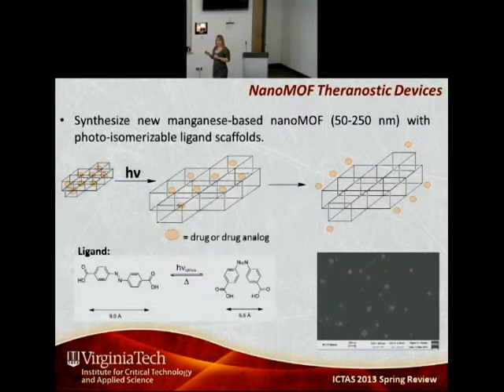You can see that these nanoparticles are very nice uniform cubes, and that's what you expect for a nice crystalline NanoMOF nanoparticle. We also confirmed by dynamic light scattering, with which Rick Davis, who just left, generously helped us, that these particles are about 130 nanometers in size.